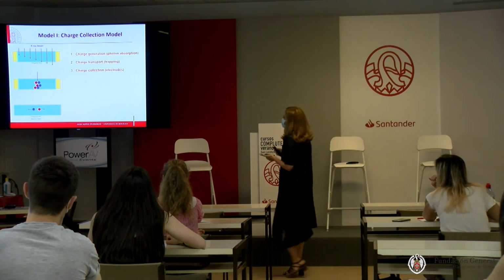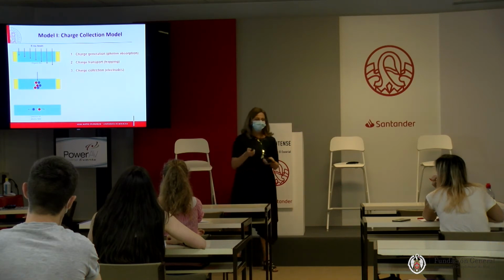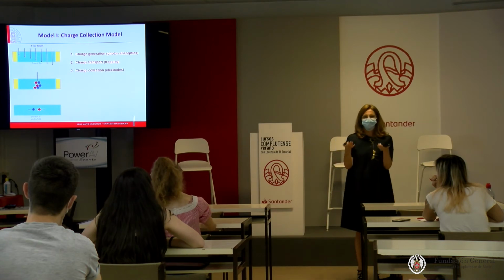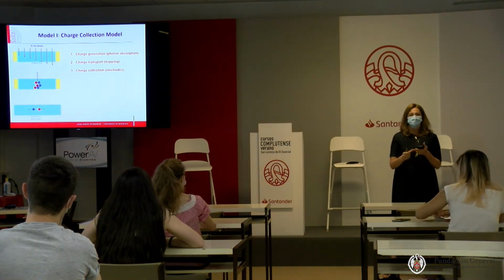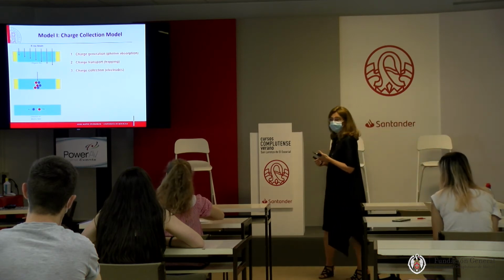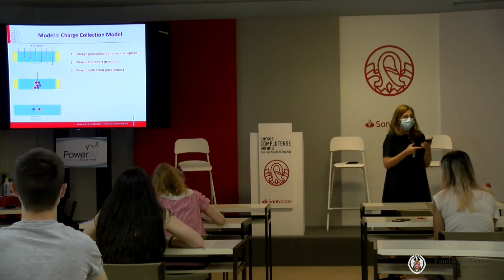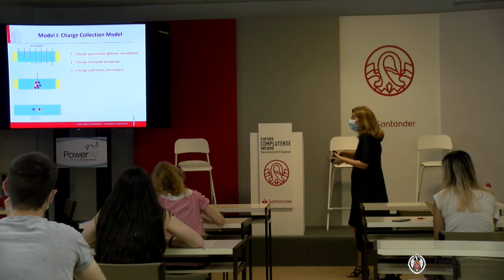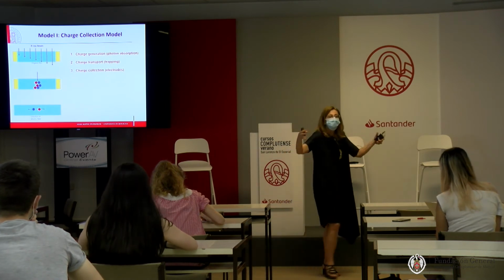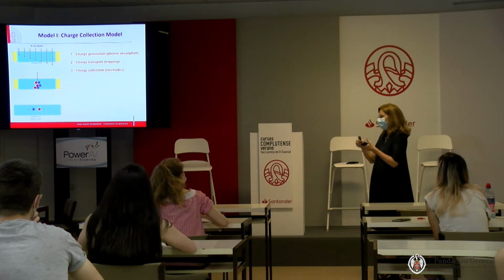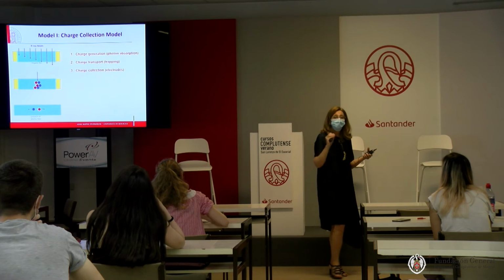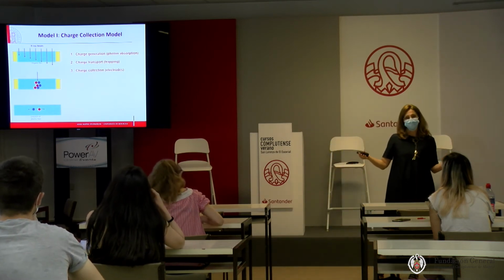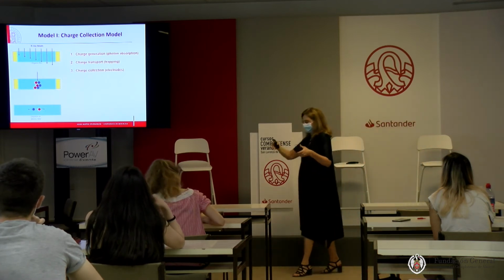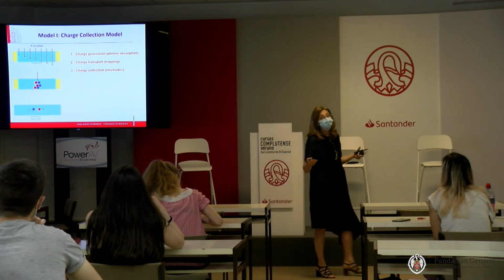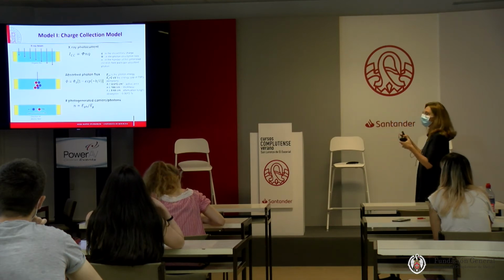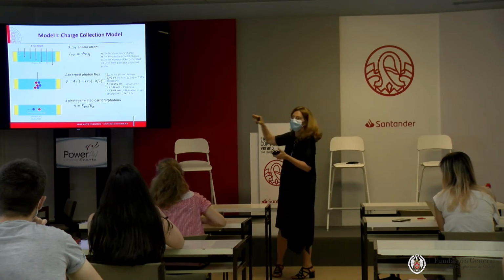Now, the key point from the physics point of view is why does it work? Because if we rely on the standard X-ray material interaction model, we have 3 major steps. Charge generation, that is related to the absorption of the X-rays from the material. Second step, charge transport, that is related to how the generated charge by each incoming photon reaches the electrodes. There, the trapping induced by defects in the material can be critical. The third step is the collection at the electrode. So the carriers need to overcome the barrier within the material and pass onto the electrodes that are typically made of metal. If we look at these 3 steps, now forget about all the calculation, but what I'm showing you is the 3 steps process.